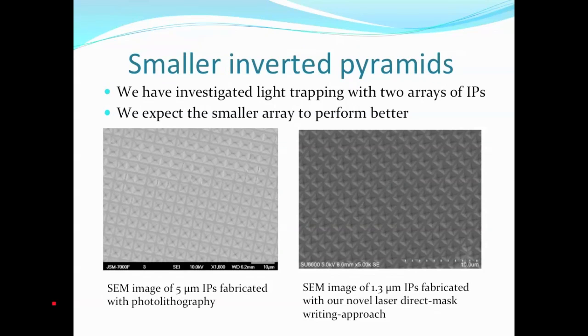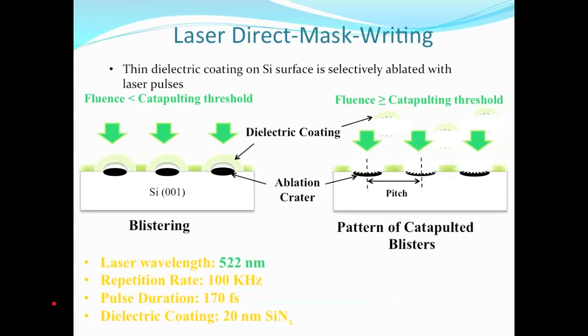In this study, we've investigated two inverted pyramid textures for silicon. On the left here, we have a scanning electron microscope image of 5 micron inverted pyramids fabricated with photolithography. 5 micron refers to the base of the pyramid. On the right here, we have 1.3 micron inverted pyramids fabricated with our novel laser writing process, which I'll describe to you. Due to the fact that the 1.3 micron pyramids are smaller, we expect them to perform better on a solar cell. So how do we make these inverted pyramids?